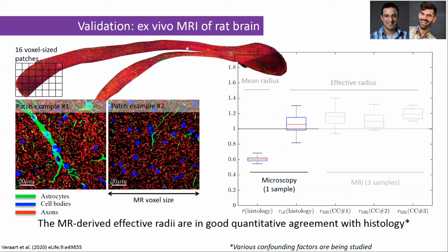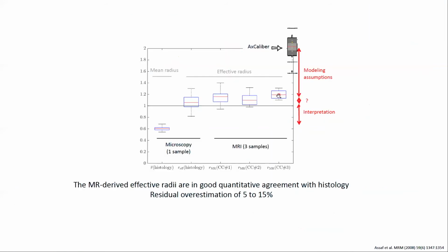This brain and two other brains, we went to the MR scanner. We have location-matched voxels. So we get an MR value of the effective MR radius in every voxel. So we can make a similar box plot. And what you can see is that the values that we compute for MR are actually in good agreement with the effective radius that was predicted from histology. There's a small remaining offset, which can relate to various confounding factors.